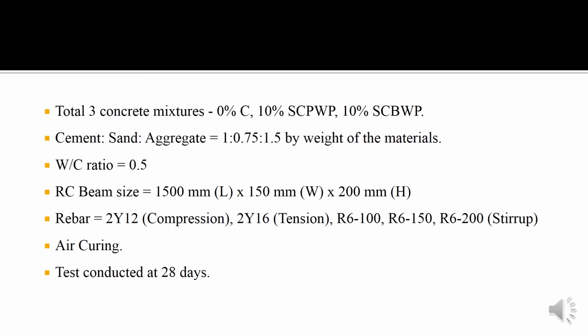Shredded copier waste paper and shredded cardboard waste paper are used as additions in concrete at 10% by weight of the mixture. There are three concrete mixtures used in this research: 0% C, 10% shredded copier waste paper, and 10% shredded cardboard waste paper. The cement:sand:aggregate ratio used in this research is 1:0.75:1.5 by weight of the materials, and 0.5 is the water-to-cement ratio used. This ratio is fixed for all specimens.